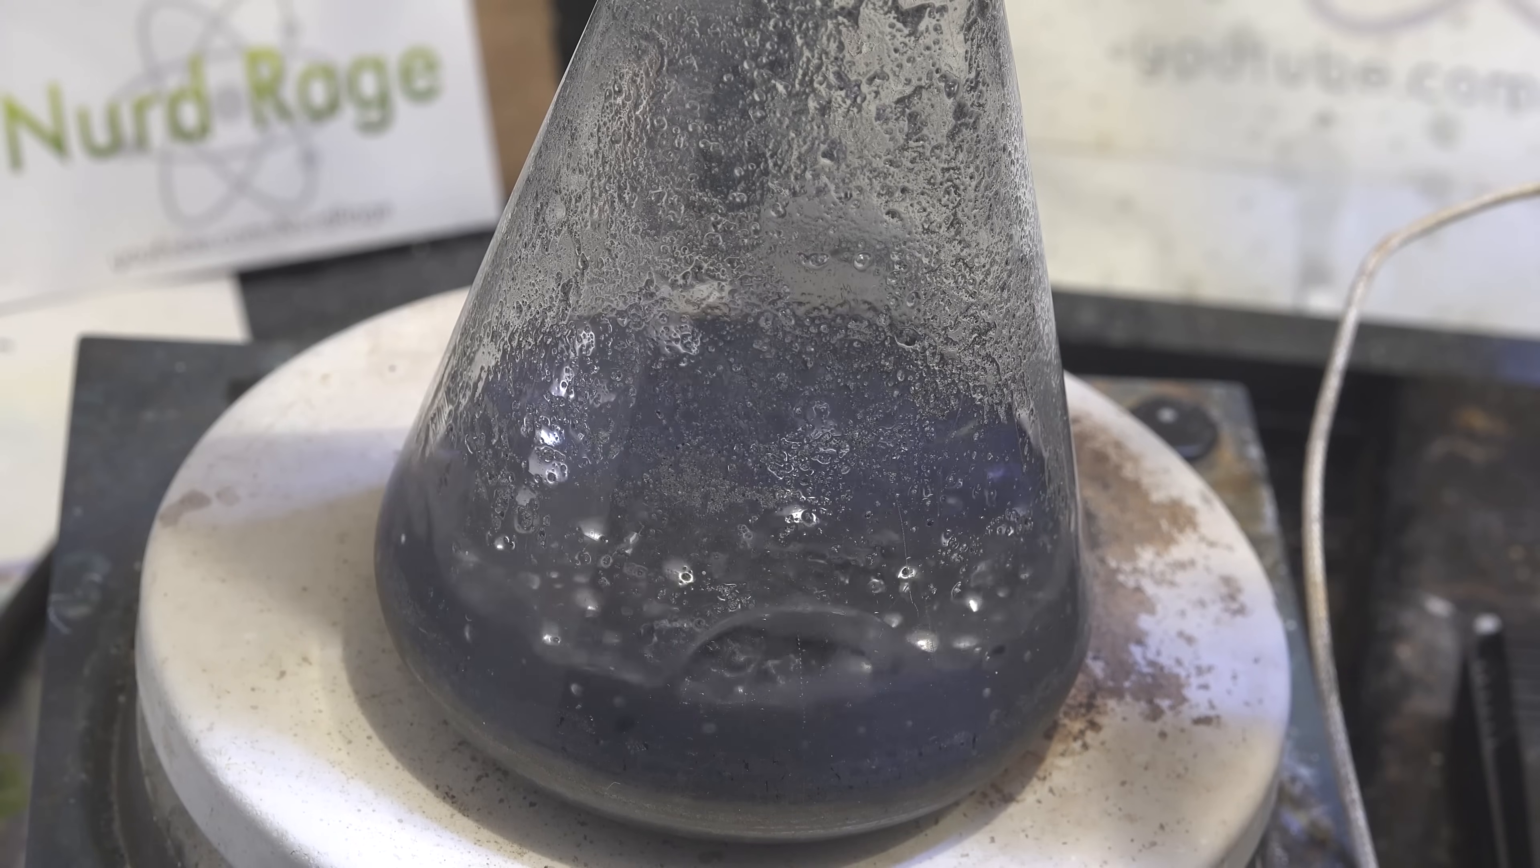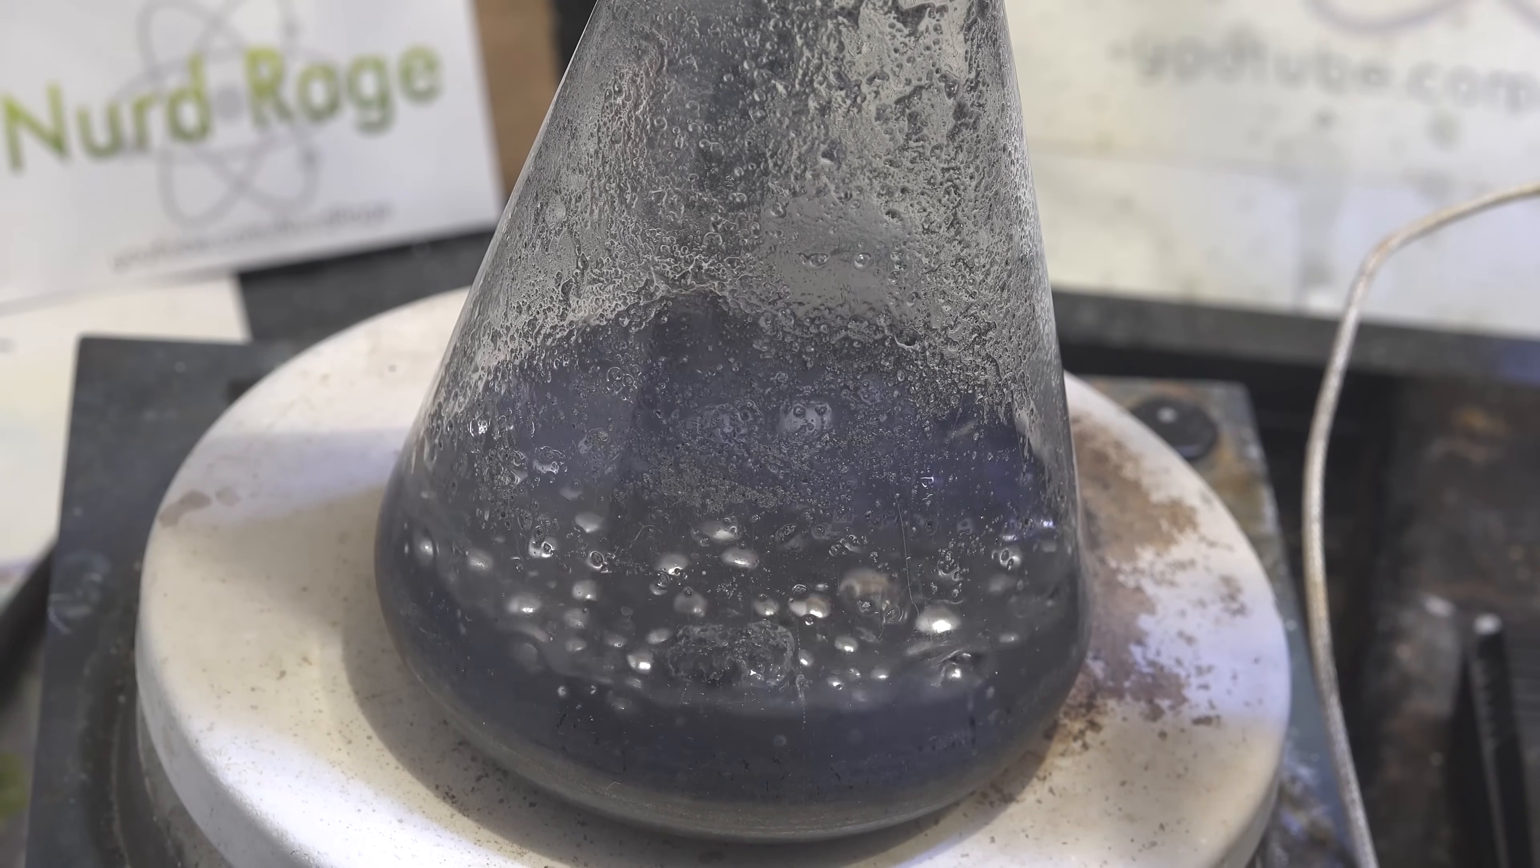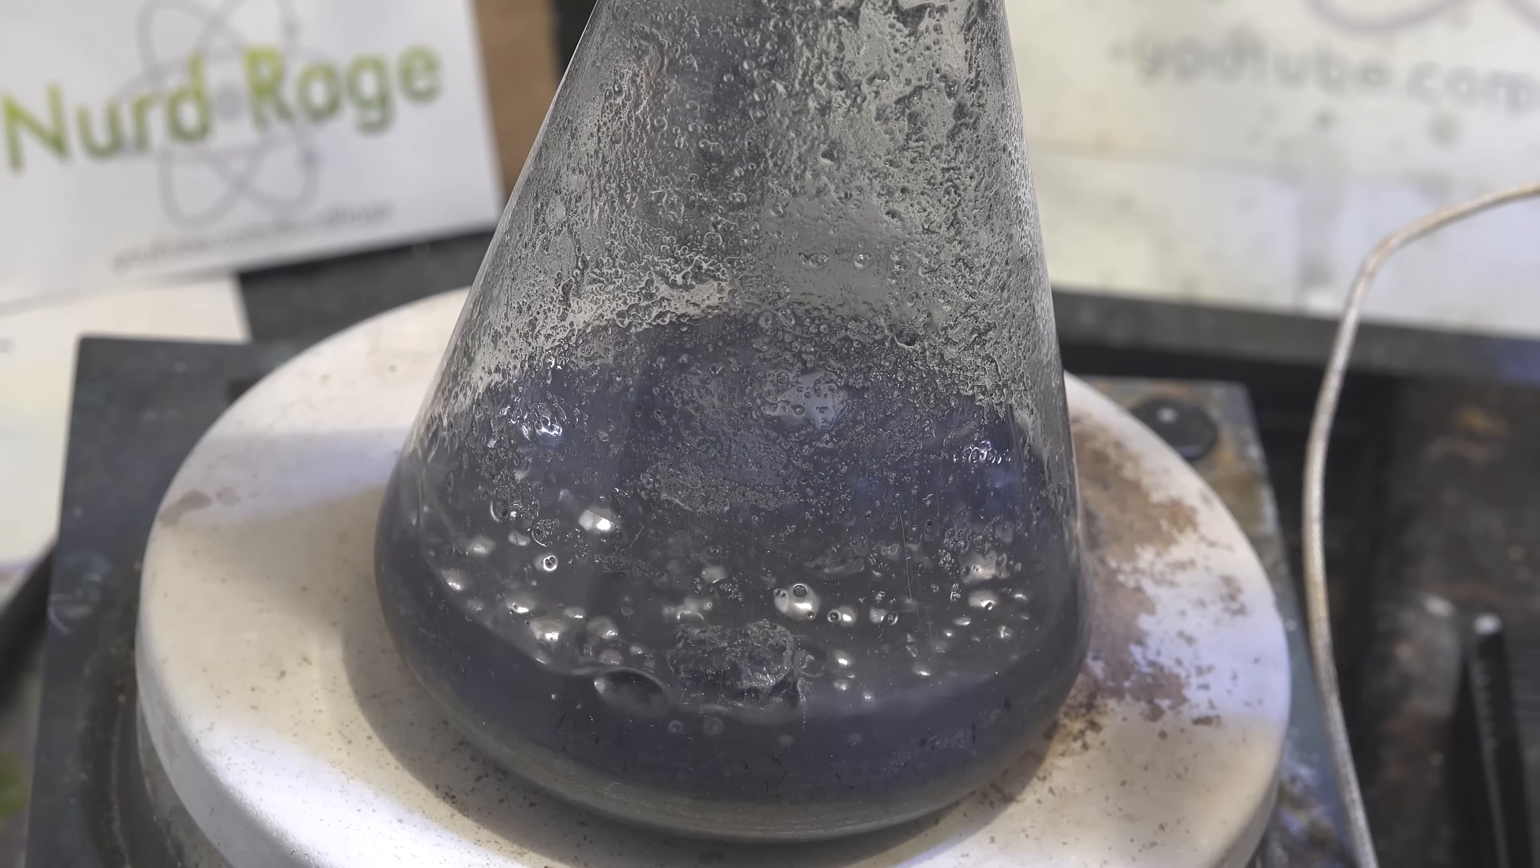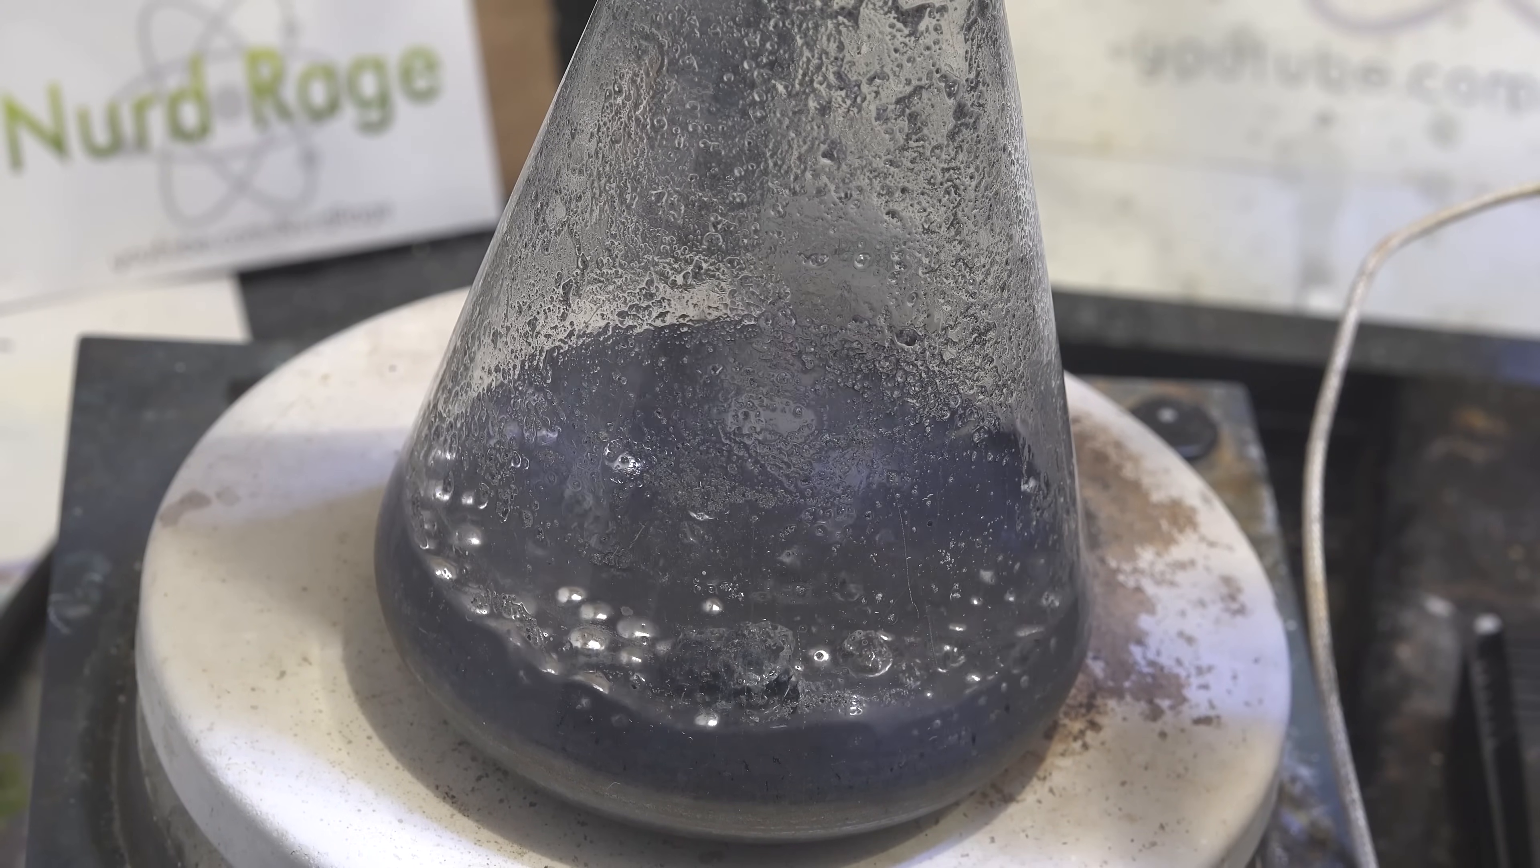Okay now at this point slow down the stirring to a minimum but don't stop. We need the stirring reduced to gently push the sodium together and encourage coalescence, but not strong enough to break apart the globules again. The original job of the stirring to break apart the aggregate and release the sodium is complete. Now keep distilling the dioxane all the way to dryness. You can see a huge globule of sodium in the back as it picks up many of the smaller sodium globules.